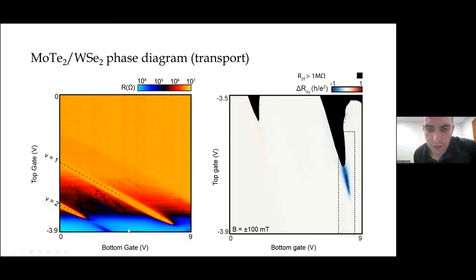So I'm now showing that same data on the left in the top gate and bottom gate axes. And I'm showing a region zoomed in around the bottom of the left plot, but showing anomalous Hall resistance. So you can see that right after the closure of the exchange gap at one hole per unit cell, there is a large increase in the anomalous Hall resistance. And the color axis here is in units of the von Klitzing constant. So indeed, you can see that we're reaching quantization in this regime.